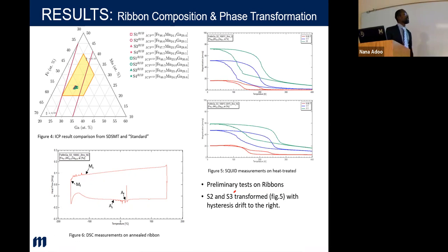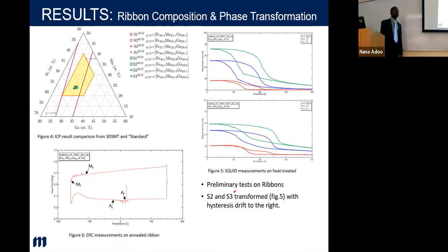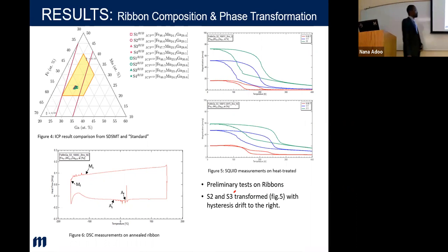And you could see very large hysteresis in there, as in when the field was ramped, you could see the band widening, then drifting to the right. And one thing for sure is that whatever is being shown here is being confirmed on the SQUID, as in when the transformation temperatures begin. And you could see from these bends,